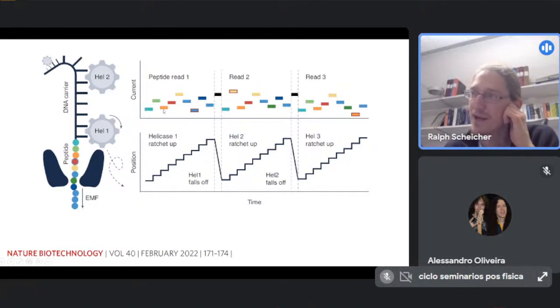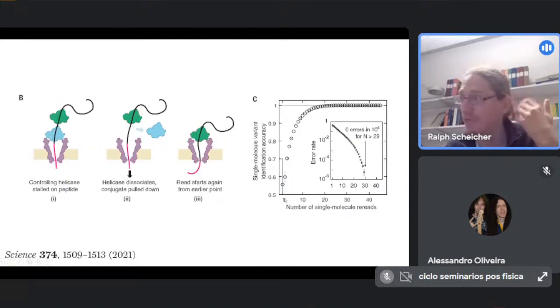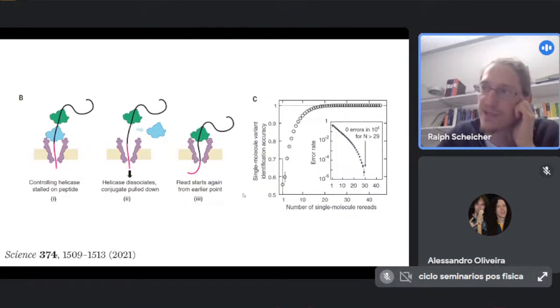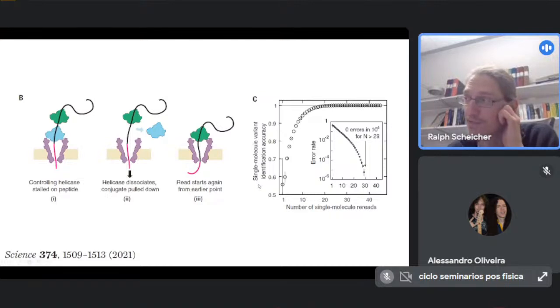And so you read the amino acids in the peptides many, many times. If you make an error in one reading, then in the next reading, it's probably going to be corrected. So after a certain number of readings of the peptides, the identification accuracy very quickly converges asymptotically to 100%, basically. So if you read maybe 20 or 30 times the same peptide chain, you have almost complete certainty that you read it correctly. So this is a very nice approach. It's nothing anywhere near something that you can commercialize yet, but it's a nice proof of principle that with this approach, you can actually identify different amino acids, at least a few of them. This was not all of the amino acids, I think, with this nanopore approach.